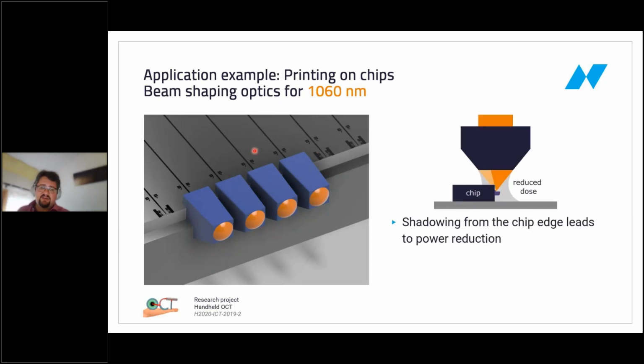This actually introduces one more challenge. If you want to print to the side of a chip like this, you will encounter a so-called shadowing effect from the chip edge. Basically, not the whole cone from the objective reaches the bottom of the printing structure anymore, but there's some light that gets blocked and reflected or scattered away. And this will lead to a power reduction at the focal point, to a reduced dose. And as you've seen, this is a nonlinear dependence, so this will very strongly affect the power that you can deposit there, and it will very strongly reduce the quality of the structure.